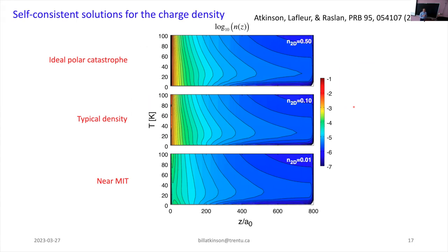Okay, and so these are the results. I'm showing three sets of results here. The horizontal axis is distance into the substrate. So I have 800 layers of strontium titanate. The lanthanum aluminate is not in this picture because it's just inert, but it's off to the left. So zero is my interface, 800 is the back wall. And the vertical axis here is temperature, so between zero and 100 Kelvin.